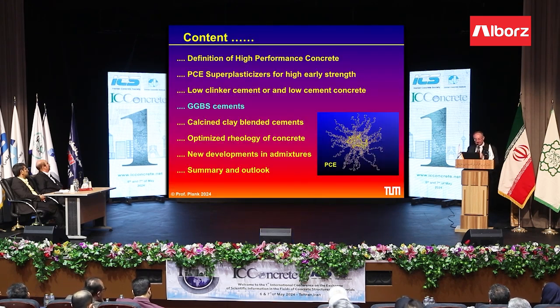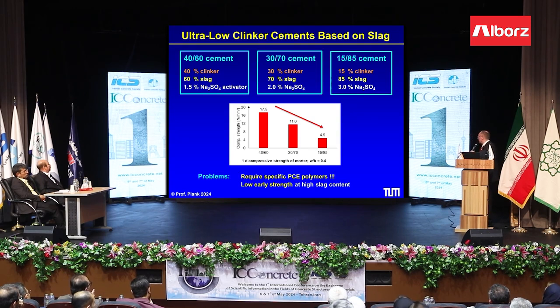Now about slag cements, especially in some countries like Vietnam, India, slags are very abundant, and a lot of work is done. Also in Western Europe, like in UK, France, and we cooperated with some companies on these low clinker cements. You can see we reduced the clinker content to 40%, 30%, 15%, and at the same time increased the slag content. So here you can see the clinker is no longer really a main component, it's the slag. And because the slag reacts relatively slowly, we need an activator, an alkaline activator. Here we use sodium sulfate.